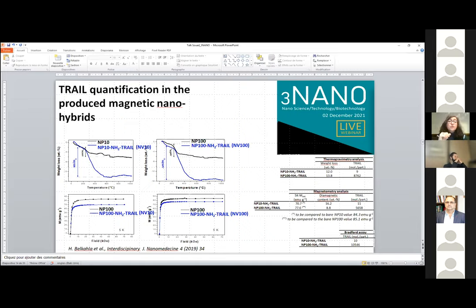Also, we decided to quantify the amount of TRAIL attached to the particles. So we used several routes. We used, for instance, thermogravimetric analysis, the weight loss being due to the TRAIL decomposition or departure from the surface of the particles under heating. We also used magnetometry measurements. Typically, we deduct the diamagnetic contribution of TRAIL from the total magnetization of our particles. And we also used some biological assays called Bradford assays, to quantify the amount of protein attached to the particles. And by this route, we obtain that we have more or less 10 molecules at the surface of the particles of 10 nanometers in size, and around 10,000 molecules at the surface of the particles of about 100 nanometers in size.